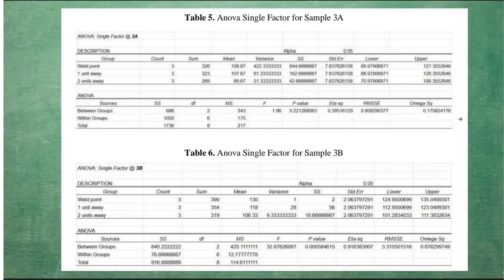For table 5, we have a p-value of 0.2213, which exceeds the 0.05 level. Therefore, we fail to reject the null hypothesis, concluding that the measurement location did not produce significant differences in hardness values. For table 6, we have a p-value of 0.00058, which is well below the 0.05 threshold. Therefore, we reject the null hypothesis. With an omega squared value of 0.876, this sample demonstrates the strongest effect size among all groups, indicating that distance from the weld point has a highly significant influence on hardness.